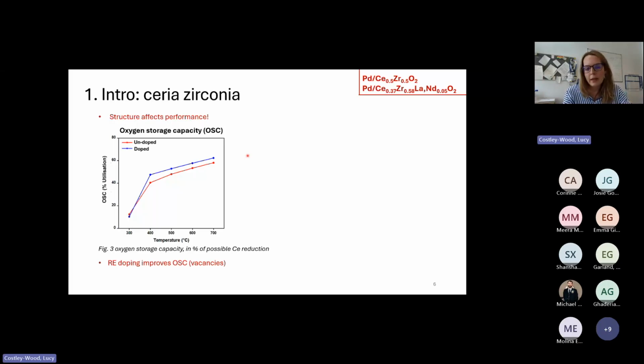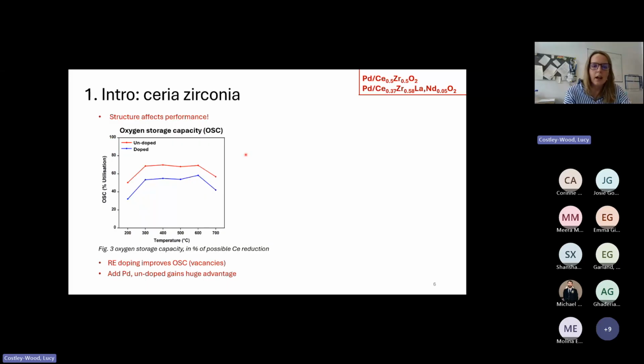However, we don't use bare ceria zirconia, we use platinum group metal doped ceria zirconia. So when we look now at the same material but with palladium on, suddenly our undoped material has a huge advantage and it performs much more superior.